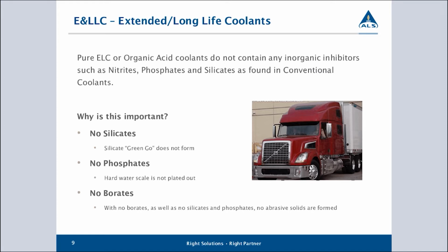Your extended life or long life coolants will often advertise, or are easily identified by the fact, that they do not contain silicates, phosphates or borates. The reason they're advertising this is that the presence of these additives can form solids in the coolant. This is the problem I was referring to earlier when I said people were overdosing the coolant. If you have too much additive present, it will tend to crystallize and form hard deposits. These can be abrasive and they can also block the system, so the formation of these compounds is not desirable in a cooling system. Anybody working with cooling systems for any length of time will have come across a cooling system that's full of a green gungy type of material, and that's the silicates forming or crystallizing within the system.